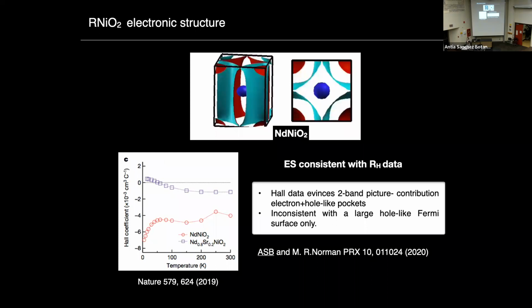The electronic structure that I just told you about is also consistent with the Hall data, and you will see me contrast theory and experiments because we always think that that's an important bit to do. What you see here is the temperature dependence of the Hall coefficient. For the undoped material in red, you can see it's negative at all temperatures, and for the doped material in blue, that it actually has a sign change. So this is already evincing that you need this type of two-band picture that I just told you about. This would otherwise be inconsistent or very hard to reconcile with us having simply a large hole-like Fermi surface like you have in the cuprates.